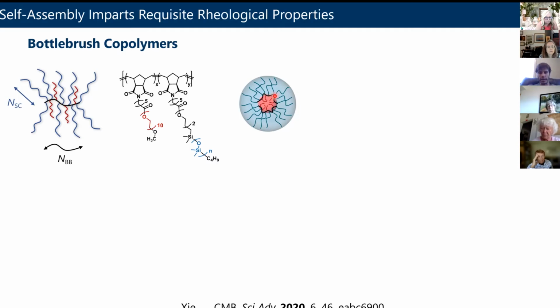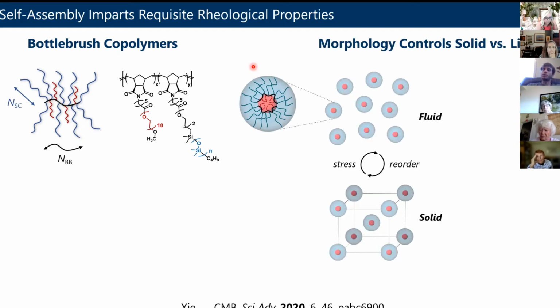And so the polyethylene oxide core of these micelles is of order 5% of the material. Everything else is this blue polydimethylsiloxane. And again, we can control the length of the red and the length of the blue and the length of the backbone. Now, why is this useful? This spontaneous process of self-assembly is particularly useful in 3D printing because these micelles, which you can see how the molecules pack into, actually order on a body-centered cubic lattice. So if you were to zoom in with an electron microscope, you would see a beautiful array of body-centered cubic spheres, which have very characteristic structure.